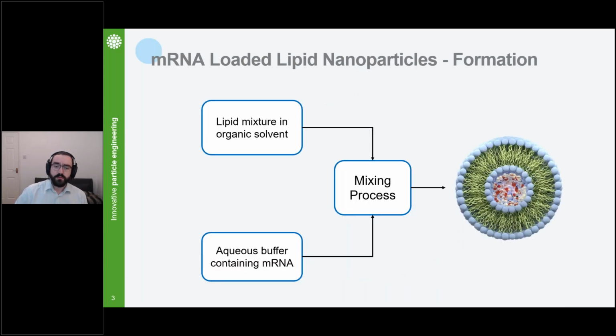The traditional way for manufacturing these materials is essentially mixing together two solvents. This is what's commonly referred to as the ethanol or solvent injection method, whereby we have our lipid mixture in an organic solvent such as ethanol, and we have an aqueous buffer solution. So if we're making these mRNA-loaded lipid nanoparticles for vaccine delivery, we're mixing those two together in a mixing process. And as that happens, our organic solvent transfers into the aqueous phase.